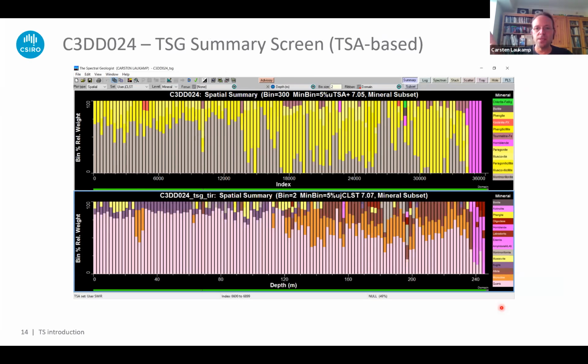This is TSA-based, the Spectral Assistant-based, which is an automated unmixing. What we are doing here is throwing random spectral data from a drill core at a spectral reference library and expecting it to give us an answer. This is quite mad, actually, but it works in many cases pretty well. But it's just the first estimate. So when you see these kinds of plots from automated unmixing algorithms, be careful, don't interpret too much into it, but it gives you a good first overview of the drill core. In this case, if you look at the different colors from the top, we see mainly different kinds of micas in yellow and smectites potentially in brown, which would be interesting. And at the bottom everything is purple, and that's the amphibolite that the pegmatite is intruding. So we have the contact between the amphibolite and the pegmatite intersected with this drill core, which is maybe an interesting point to look at.